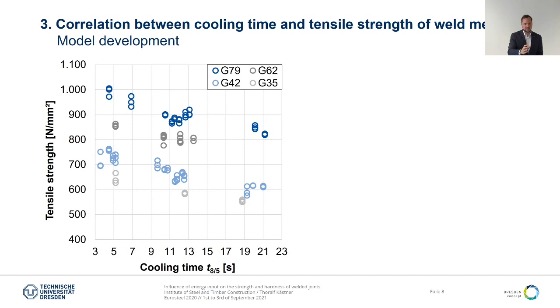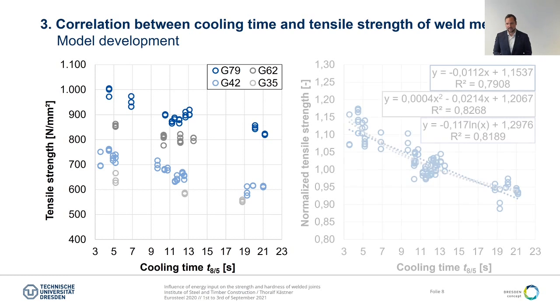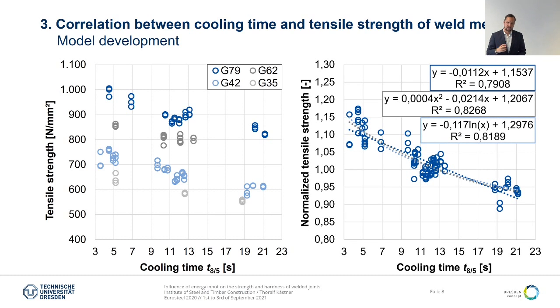What we can see here are all the test results we achieved with these different filler metals, and of course here we can have a look at these results and describe the correlation of tensile strength and cooling time t8/5 for each filler metal on its own, but we cannot compare the results in a good way. So therefore we decided to normalize the tensile strength to the cooling time of 12 seconds.